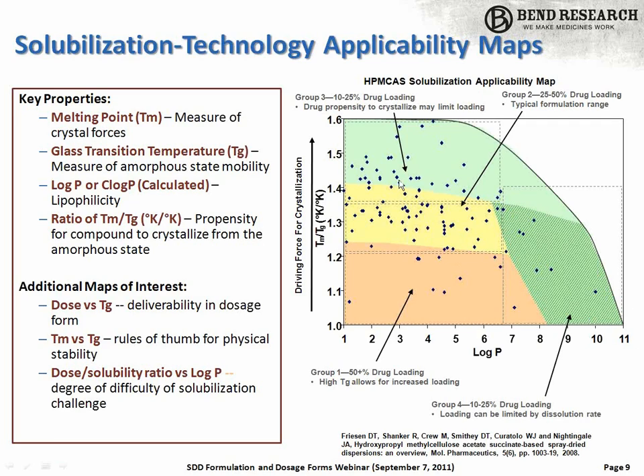Looking at the map: up in the upper left-hand corner, you have very highly crystalline compounds with very high melting point and strong driving force to crystallize. The challenge is preventing them from crystallizing out of the amorphous state, so typically one has to operate at fairly low drug loading or low drug-to-polymer ratio formulations. In the lower right-hand corner, you see extremely lipophilic compounds at fairly low driving force to crystallize — sometimes even oils at room temperature. Due to their extreme lipophilicity, you can have difficulty getting rapid dissolution rate even when combined with polymer, so those also typically require relatively low drug loading STDs, or sometimes nanoparticles or other technologies.